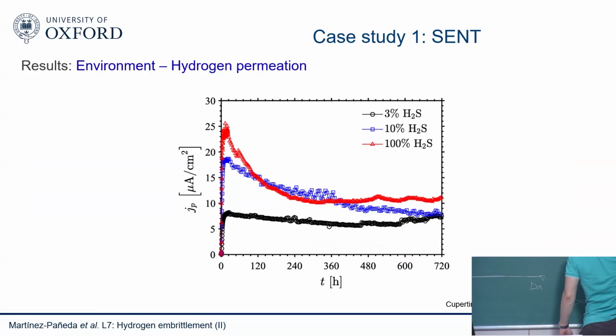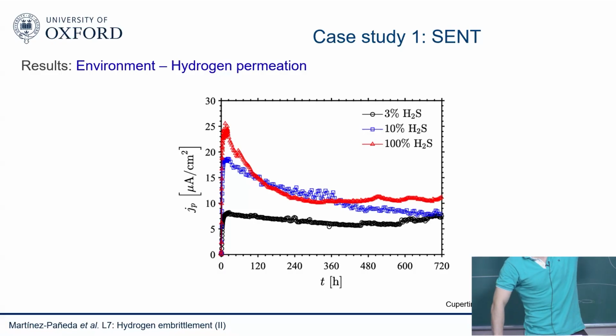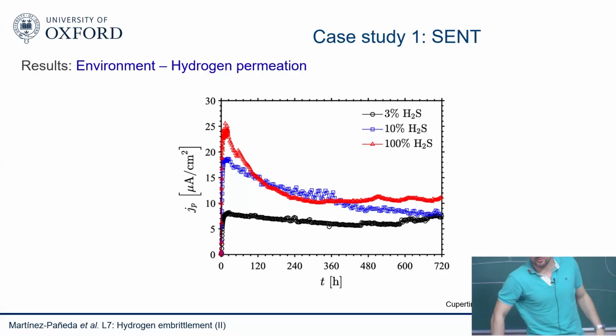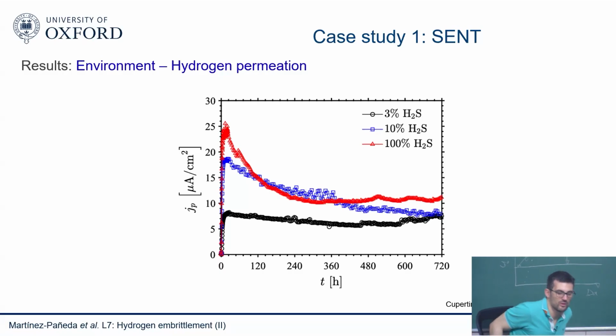There was a bit of a scatter, but they're all looking something like this. So it's growing, and then eventually you get some sort of steady state. Here you can see that it's a bit different. The thing is going up initially, but then something happens and then it goes down. And this is basically the fact that you form an oxide. By the way, this is for various H2S concentrations.